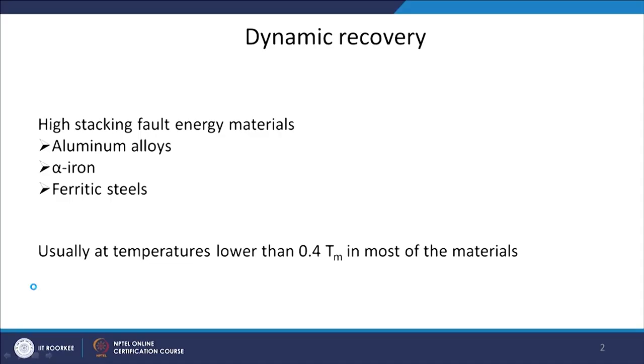If you define where dynamic recovery will be an important process: in terms of materials, high stacking fault energy materials — that is, materials which have high stacking fault energy — these kinds of materials show predominantly dynamic recovery instead of dynamic recrystallization. They show dynamic recovery.